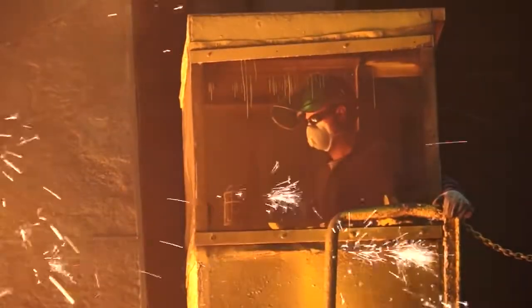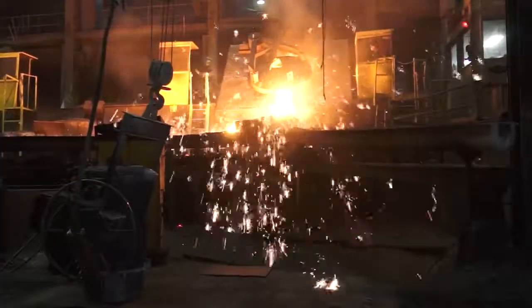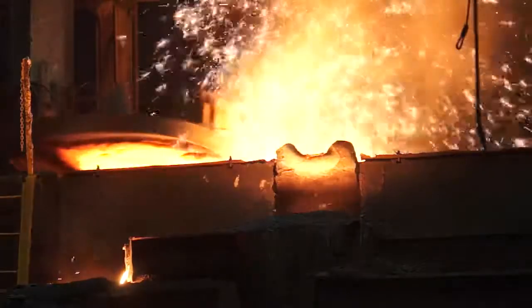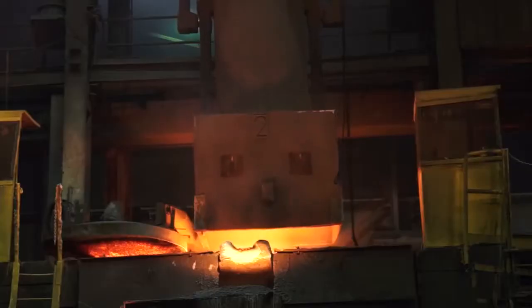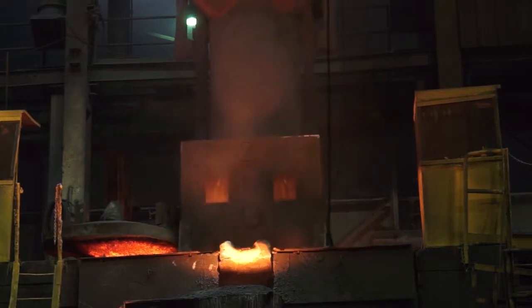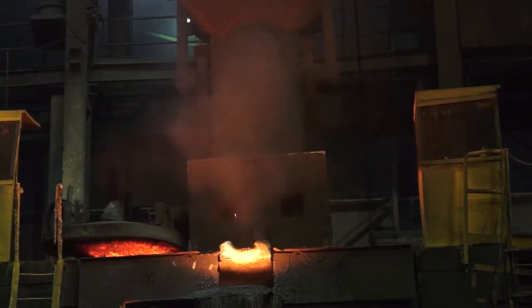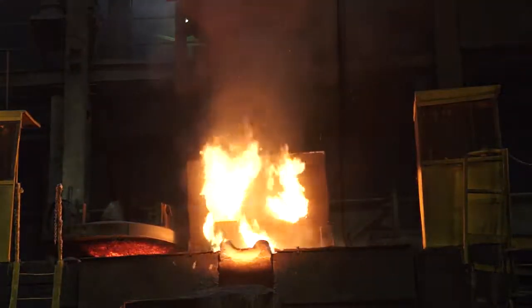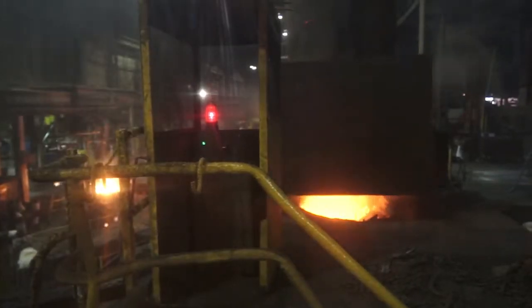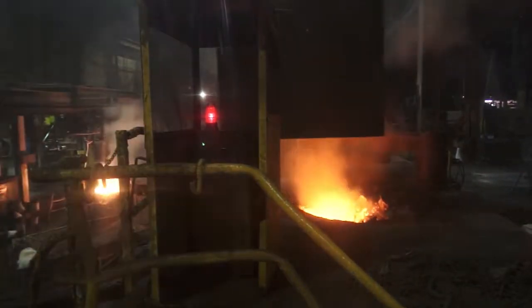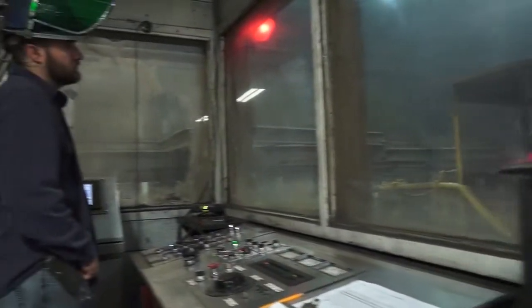American Castings' melting department uses 3 23-ton induction furnaces and 3 30-ton holding furnaces. This combination of melting and holding produces an extremely clean base iron with consistent physical and chemical properties. The plant produces 3 grades of gray iron and 4 grades of ductile iron, with ductile iron accounting for 80% of the castings made at the plant. A sophisticated energy management system is used to control melt energy costs.